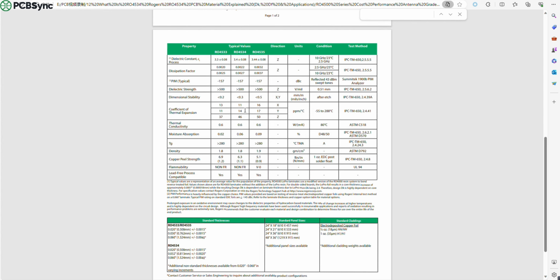The coefficients of thermal expansion, CTE, of RO4534 in the X, Y, and Z directions are 11, 14, and 46 parts per million per degree Celsius respectively. Its thermal conductivity is 0.6 watts per meter Kelvin, and its water absorption rate is 0.06%. The TG, glass transition temperature, of the RO4500 series is all above 280 degrees Celsius, and they also offer excellent dimensional stability. These characteristics help large antenna boards maintain structural stability during processing, installation, and temperature changes.